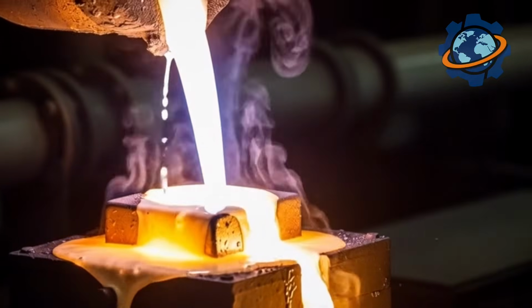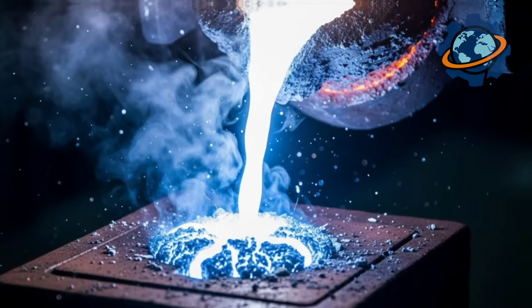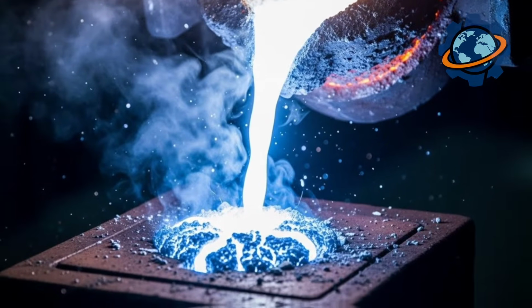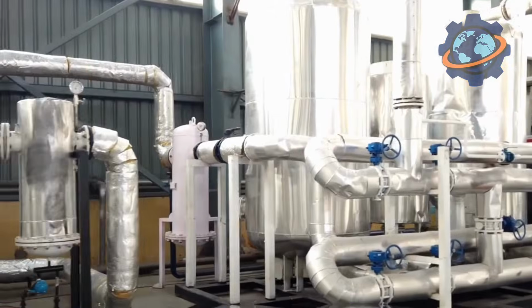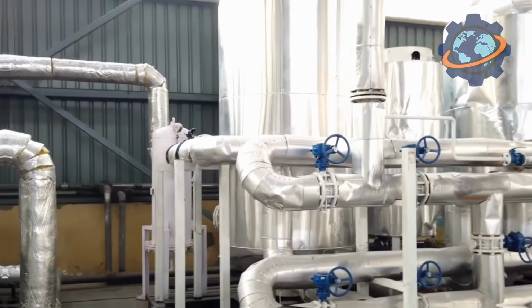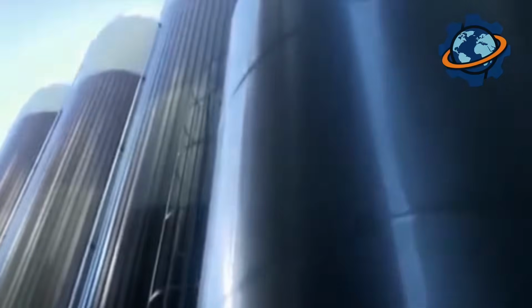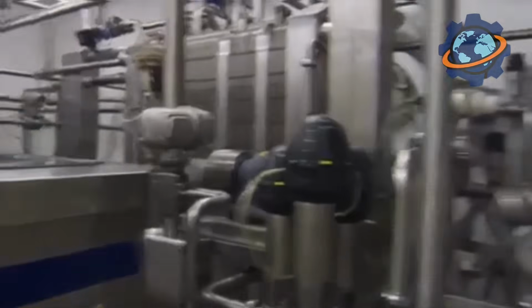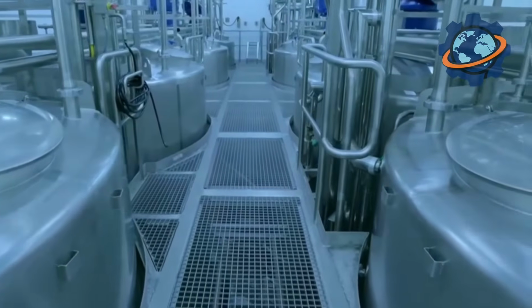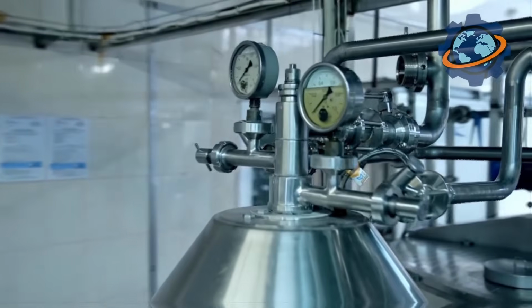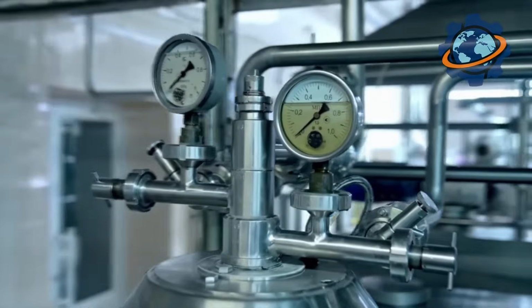These furnaces evacuate to 0.0001 atmospheres, a better vacuum than low Earth orbit. An electron beam, essentially a lightning bolt focused through magnetic lenses, melts the electrode tip at 11,000 degrees. Watch through the lead glass viewport as the electron beam strikes. The zirconium glows blue-white, temperature exceeding the sun's surface.